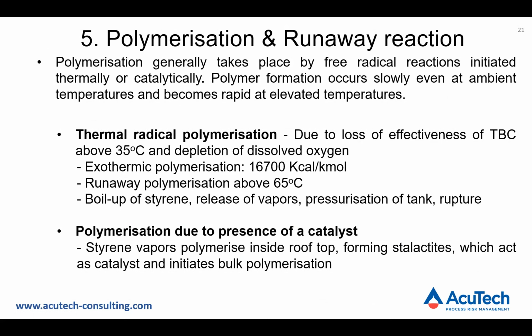Since there's evidence that effectiveness and concentration of the TBC inhibitor was reduced and bulk mixing and cooling was inhibited, it's apparent that this incident was caused by a runaway polymerization. Lack of dissolved oxygen may also have been a contributing factor, as well as the presence of polystyrene stalactites, which may also catalyze further polymerization if they contact the liquid.